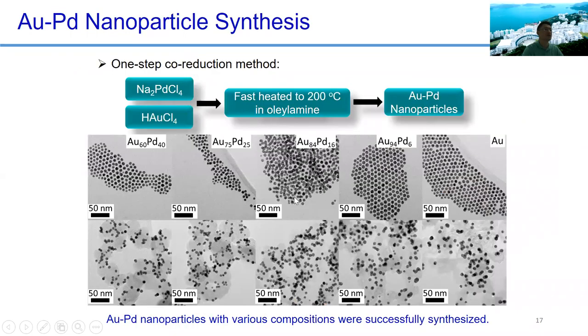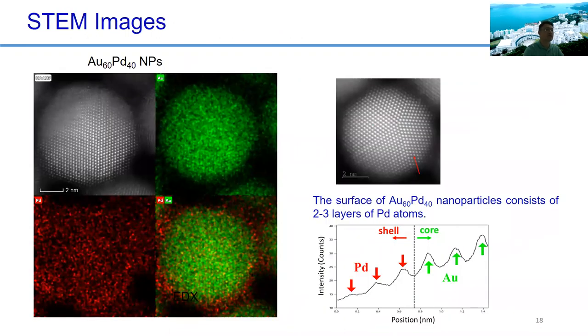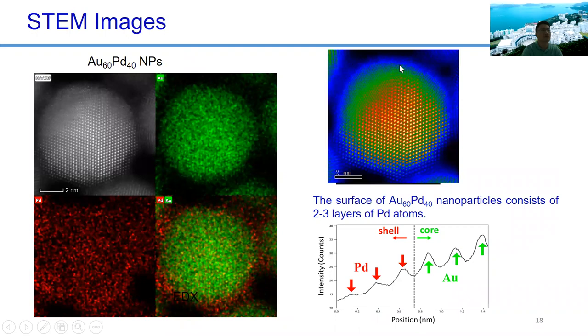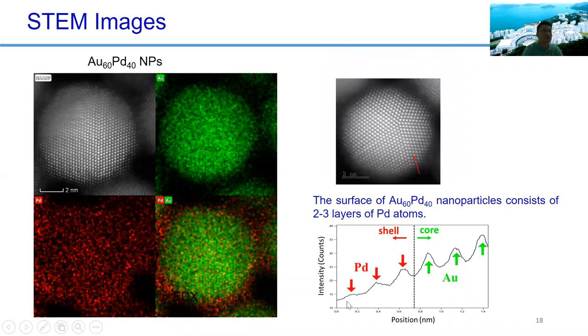Last year we did similar experiments on the palladium gold nanoparticles. These are all different nanoparticles with different compositions but similar size. We did the STEM characterization. You can see clearly that the palladium is separated on the surface. And if you do a line scan, the blue one is basically the palladium. You can see that the first two or three layers are pure palladium, and inside is the gold. So it is basically a core-shell structure.